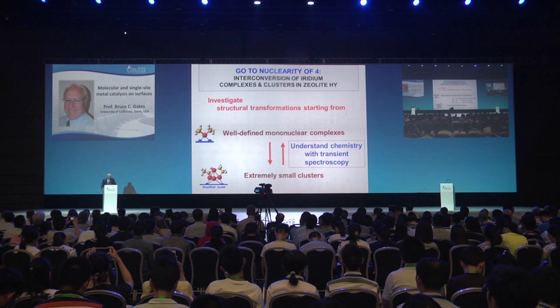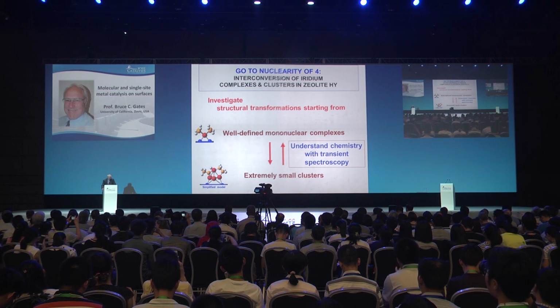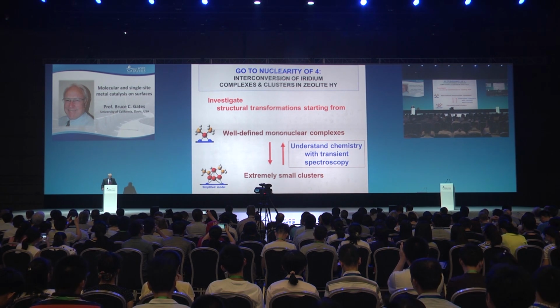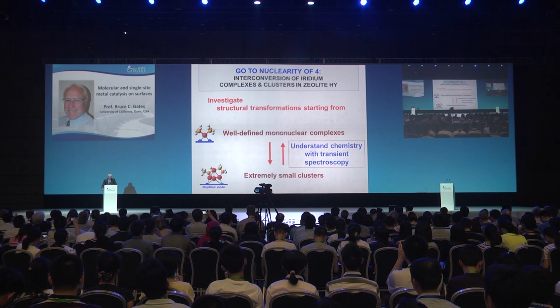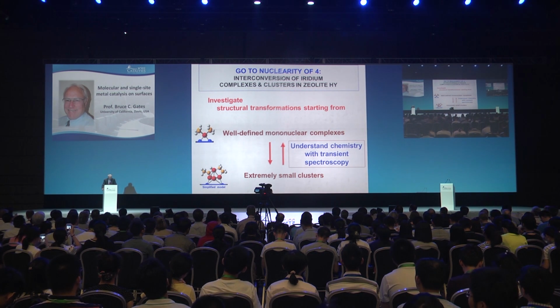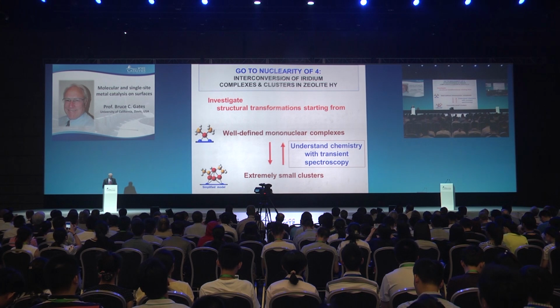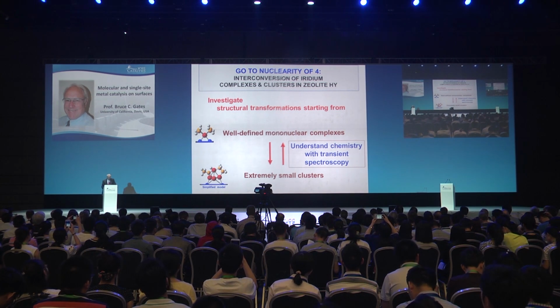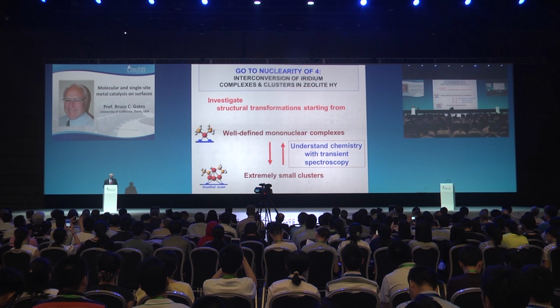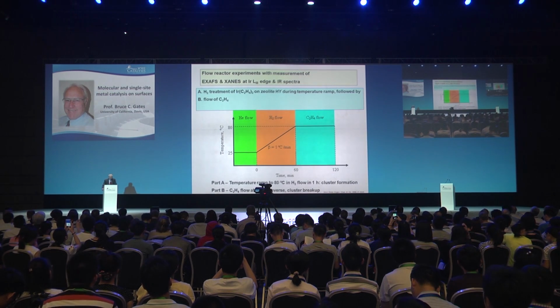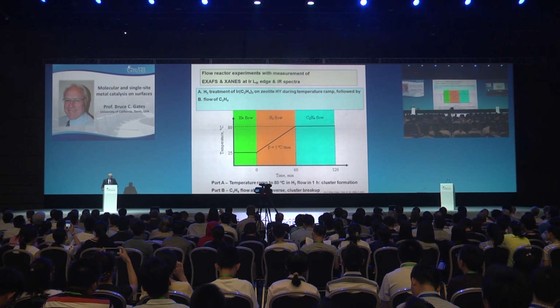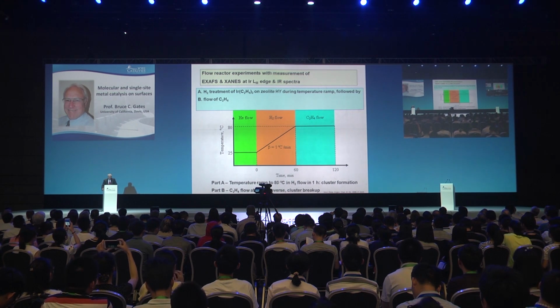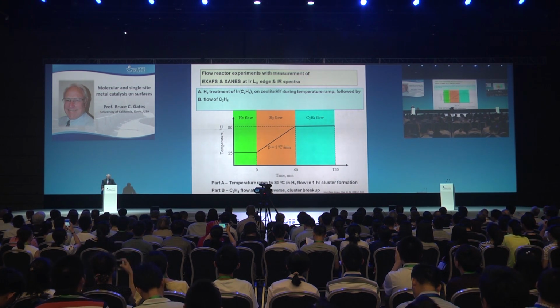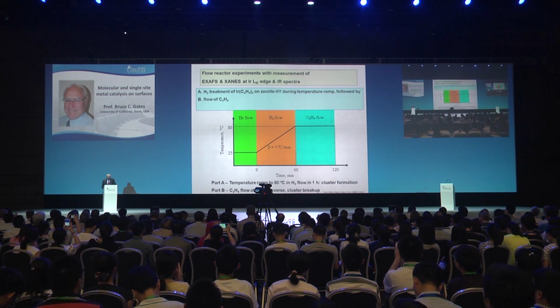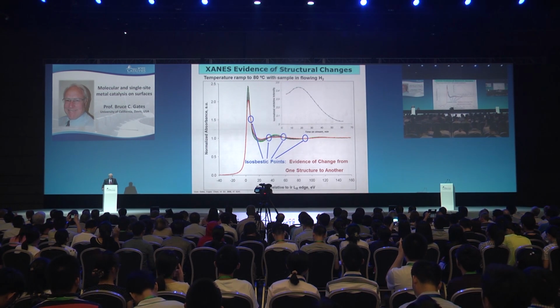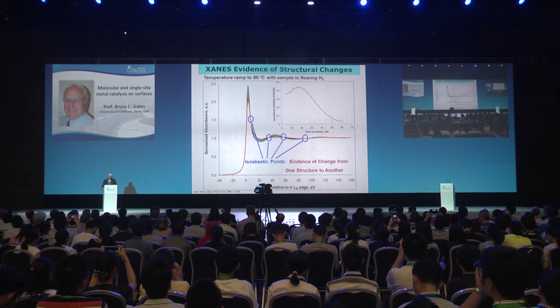Sometimes the clusters on the support can be made with high precision, and this is another example illustrating nature's kindness. We take mononuclear iridium in the zeolite and treat it under conditions that cause reduction and cluster formation. We ramp the temperature with the sample in hydrogen and make measurements of the spectra during the changes as reduction takes place.